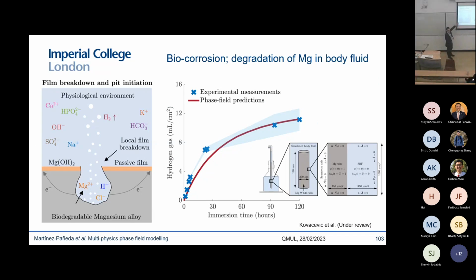And last but not least, this is my last slide, we have also looked into biocorrosion, so the degradation of magnesium in simulated body fluid. And this is quite important for scaffolds made of biodegradable materials, such that when the bone heals, there's no need for a second surgery to remove that component. And we can use exactly the same idea, and we're able to capture experiments very well.